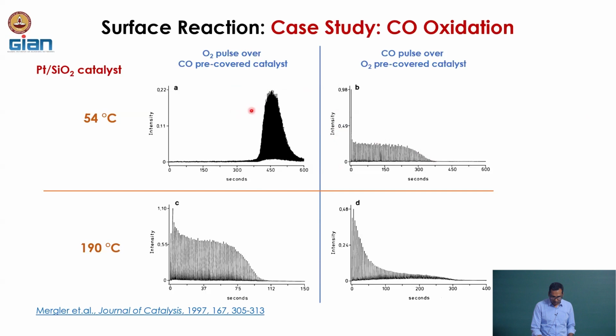But in the opposite case, if I see here, the surface is pre-covered with CO and now I am pulsing oxygen, I am not seeing CO2 for about 300-400 pulses. So, that gives us an idea that once the surface is saturated with CO, the oxygen cannot be adsorbed on the surface, and if oxygen cannot be adsorbed on the surface, the reaction cannot happen. But then what is different at 190 degrees Celsius?